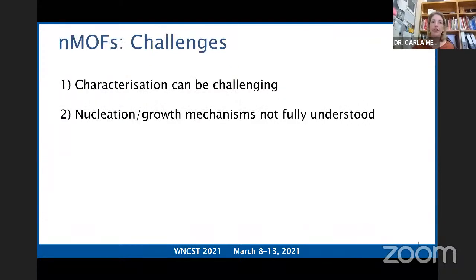So what are the challenges then? Despite the fact that nano-MOFs really can expand the scope of utility of their bulk counterparts, I think I've calculated it to be less than 0.25% of the 20,000 plus unique MOFs that have been prepared at the macroscopic scale have actually been prepared on the nanoscale. So really a tiny, tiny fraction of the known MOFs have ever been prepared on the nanoscale. In particular, nano-MOFs with diameters less than 20 nanometers are particularly rare. There are a variety of factors that have led to this disparity.